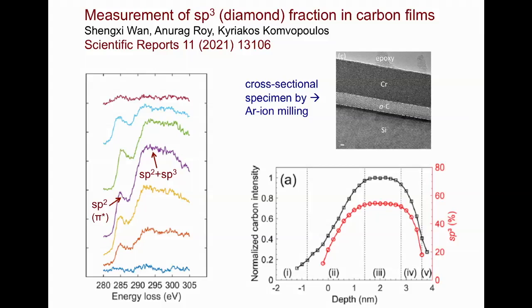The electron spectrometer has an energy resolution of the order of 1 eV, and sometimes better, sufficient to resolve spectral fine structure that can reveal the electronic or atomic structure of a specimen on a sub-nanometer scale. The example here involves amorphous carbon layers that are used as hard coatings on data recording disks and recording heads. The hardness derives from the presence of diamond-like sp3 bonding between some of the carbon atoms. But diamond is a metastable form of carbon, so there is usually also some graphitic sp2 bonding.